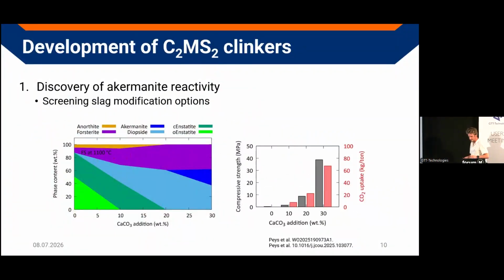And we noticed when we made some compacts and carbonated them, that with the different compositions, we made some with 0 addition, some with 10% addition of calcium, 20% addition, 30% addition. We started from a strength of 0 megapascal, but we went up to 40 megapascal with this highest addition of calcium.